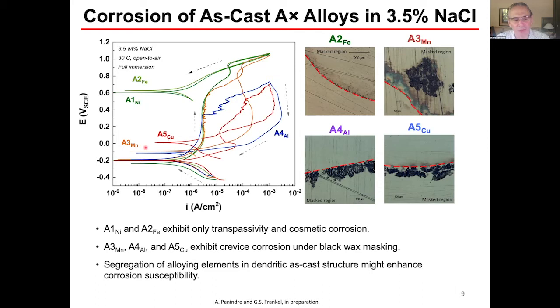These other alloys, the ones with manganese, copper, or aluminum, are susceptible to crevice corrosion, the masked region being shown separated by these lines. We can see that this was using a black wax masking. I should say this is the as-cast alloys, not the solutionized alloys, which again will promote the tendency for this to occur, but they're very, very susceptible to crevice corrosion. And indeed, it's not easy to eliminate the crevice artifact.